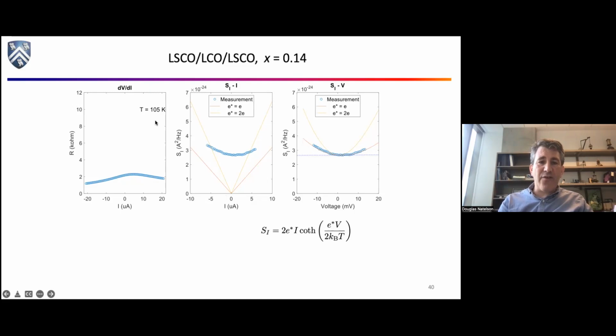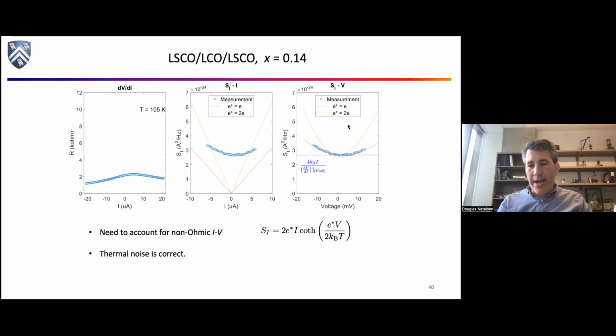Here we are at 105 Kelvin, pretty toasty warm on the scale, even though it's much colder than room temperature. It's pretty toasty warm for this material. So let's cool down and see what happens, right? I should point out at zero driving, when the thing's totally in equilibrium, the noise level here is exactly what you expect. It's exactly the thermal noise, the Johnson-Nyquist noise, that's all fine.